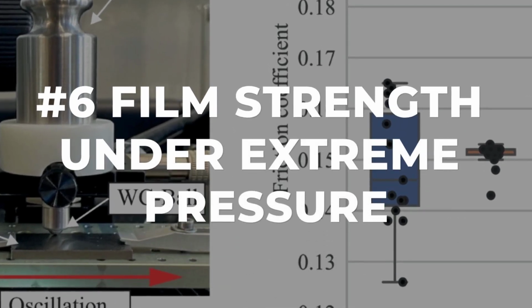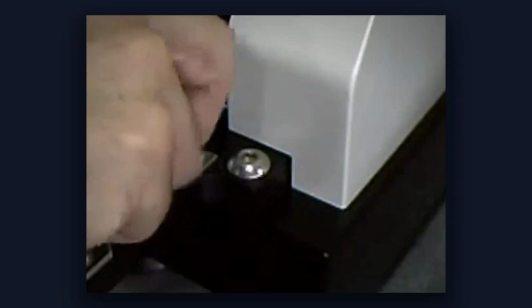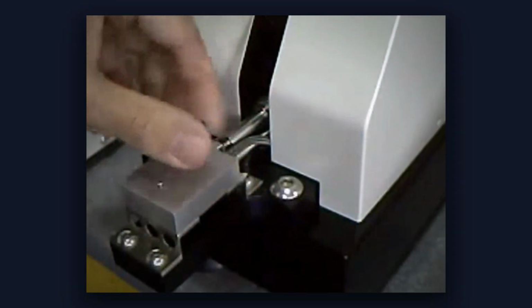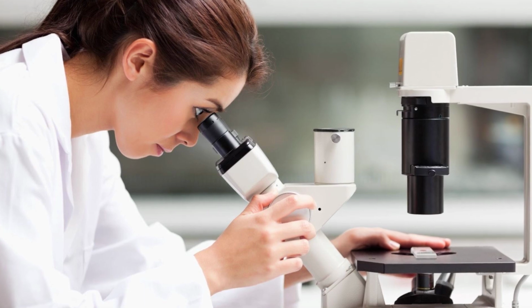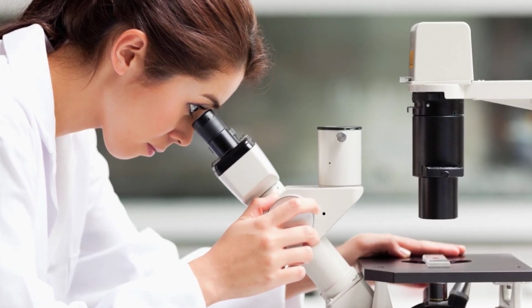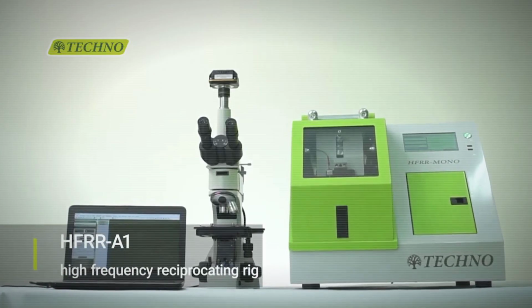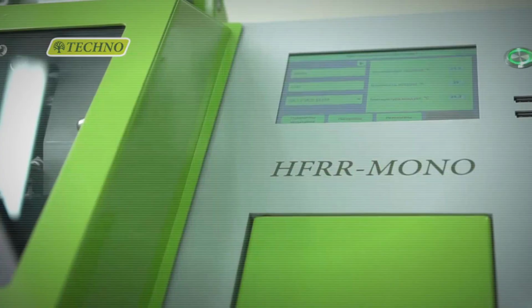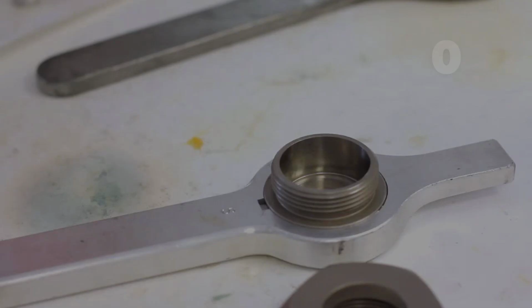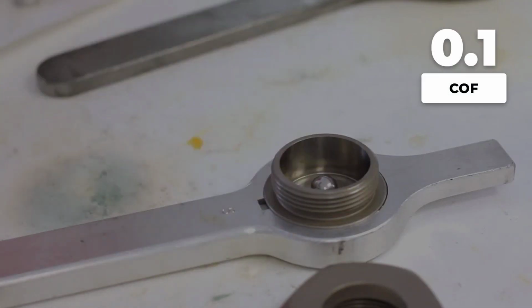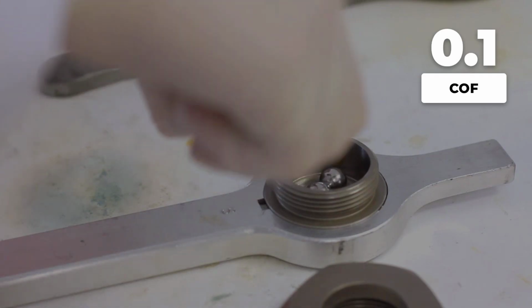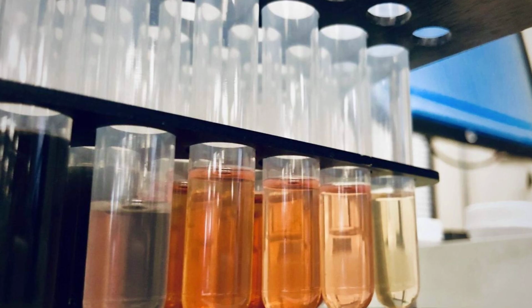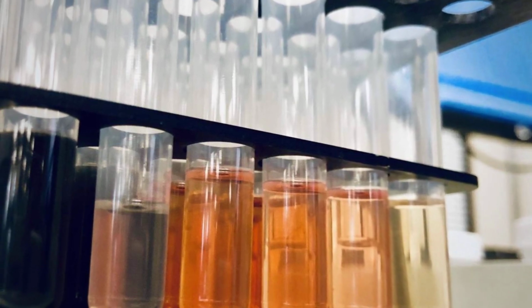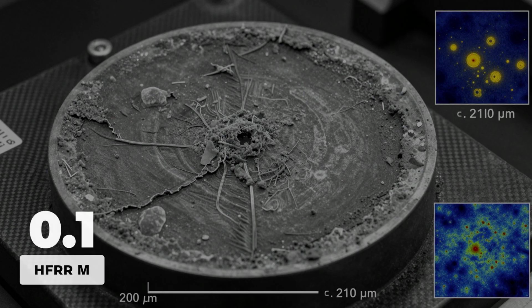Number 6. The hard numbers leave no room for nostalgia or marketing spin. In the lab, castor oil's boundary film strength is not a rumor, it is measured, photographed, and quantified. High-frequency reciprocating rig tests, the gold standard for evaluating friction under extreme pressure, reveal a steady-state coefficient of friction around 0.06 for pure castor oil. That is less than half the value typically posted by mineral oils, which hover near 0.14 under the same conditions.